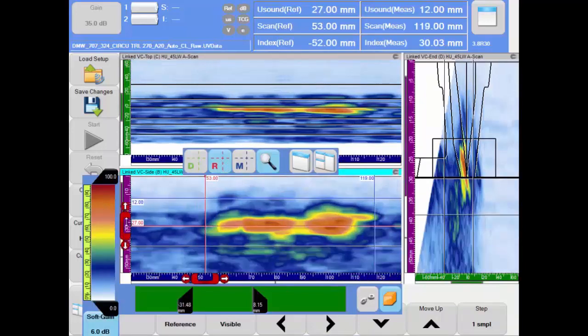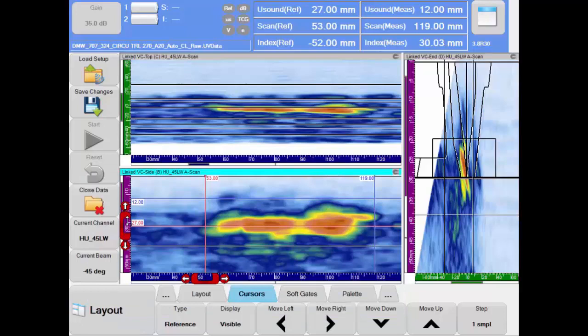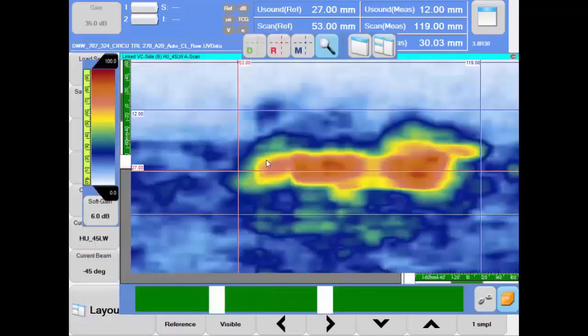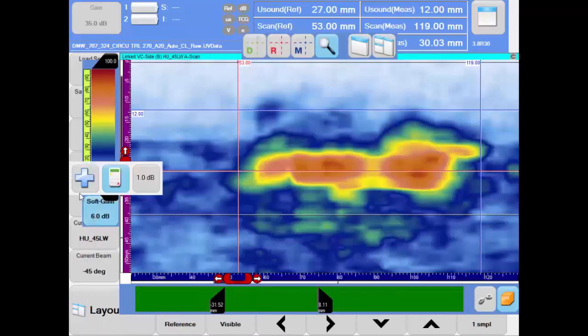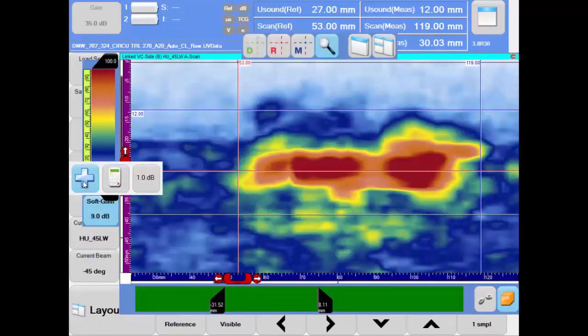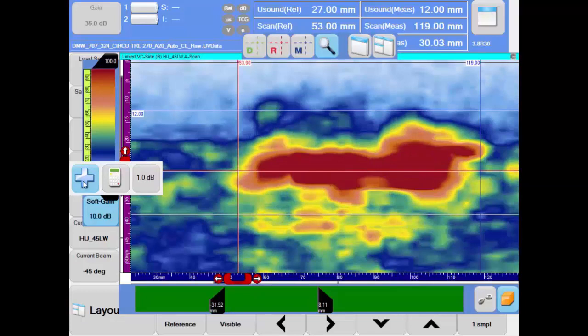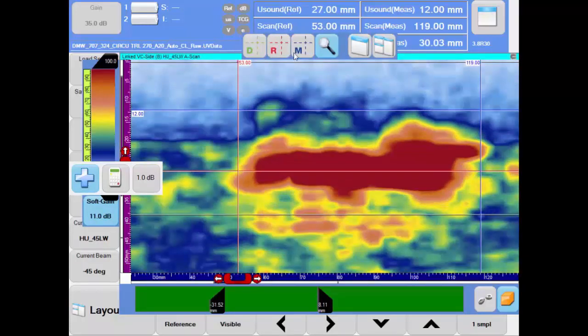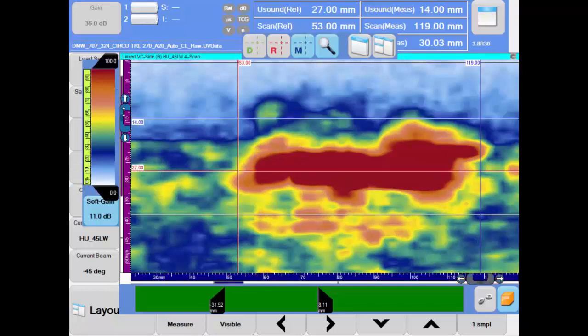The reference cursor is positioned at the center of the corner trap, and then we examine the signals above the ID surface. We will apply soft gain to see several facets of the crack lightening up. The center of the highest clearly resolved signal above the corner trap is taken into account for through-wall measurement. We position the measurement cursor, and the crack depth can be read from the information views.